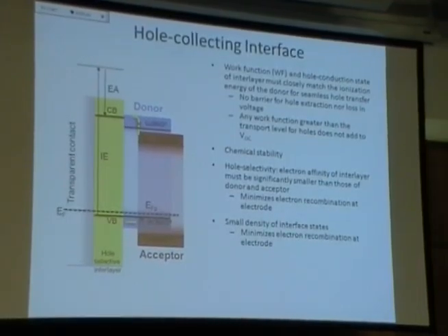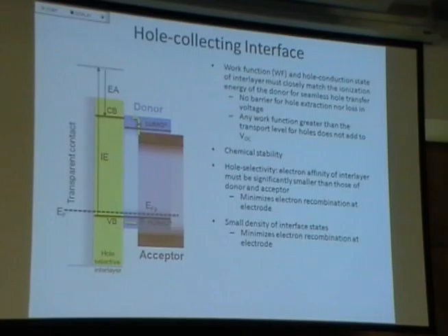What can happen in an oxide? You can form interface states. What do I mean by interface states? I mean mid-gap states. You might have a conduction band that's really, really high, but if there are little pathways, little interface states within our gap, you now have a region where those charges can leak through. You can have recombination, so it starts to undermine your selectivity.